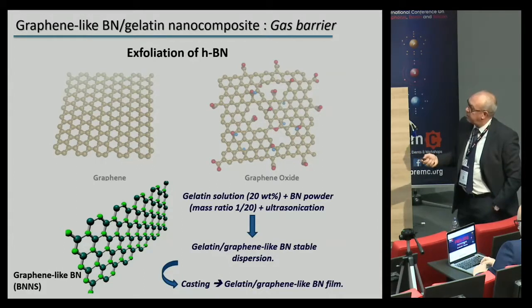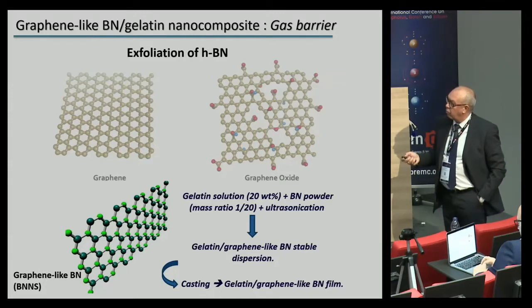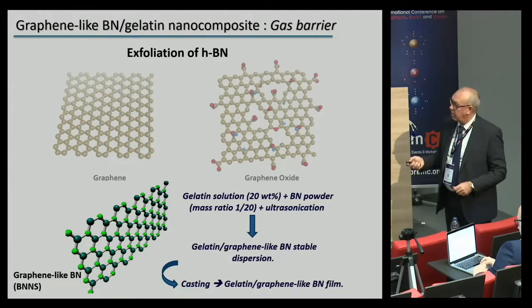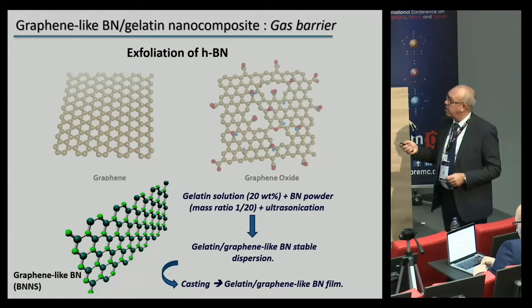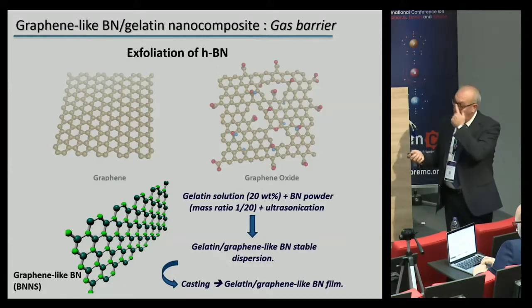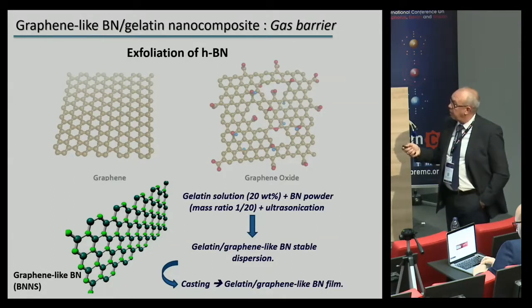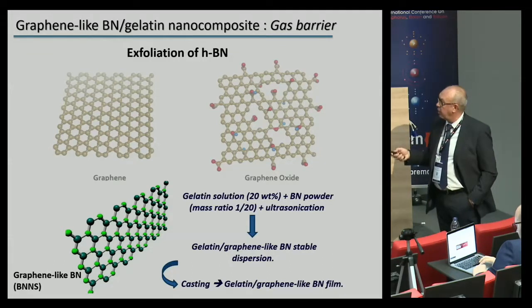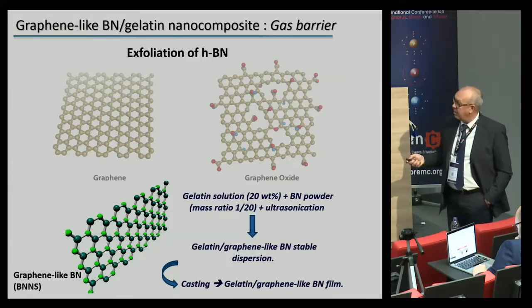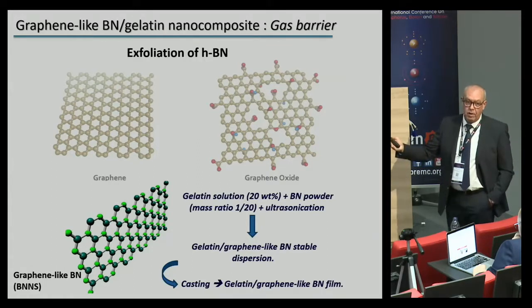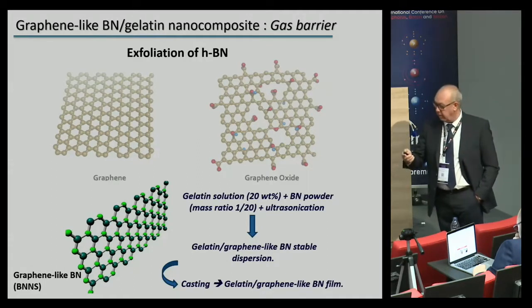You can see that these BN nanosheets can also be called graphene-like BN because the structure is almost the same. You have the graphene here and the graphene oxide here, and it's relatively easy to obtain, starting from a gelatin solution with a commercial BN powder. After ultrasonication, you obtain a stable dispersion of boron nitride in the gelatin, and this can be used directly to prepare, for example, films and after that, membranes.